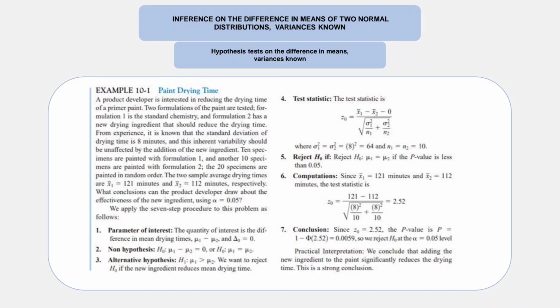The conclusions. Since the test statistic is equal to 2.52, the p-value is 1 minus the normal probability at 2.52, which is equal to 0.0059. So we reject the null hypothesis at the alpha equal to 0.05 level. We conclude that adding the new ingredient to the paint significantly reduces the drying time. This is a strong conclusion.